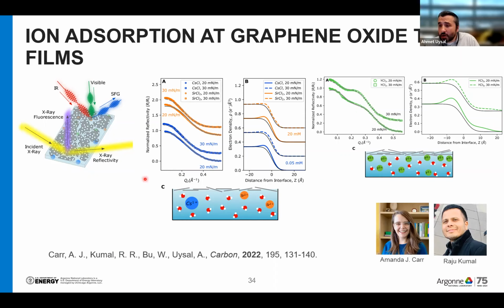Here in this study, we are comparing monovalent, divalent, and trivalent ion adsorption. There is a significant difference when you adsorb trivalent ions to these graphene oxide films, because unlike monovalent or divalent ions, trivalent ions affect the graphene oxide structure. So we are observing those changes using X-ray reflectivity.